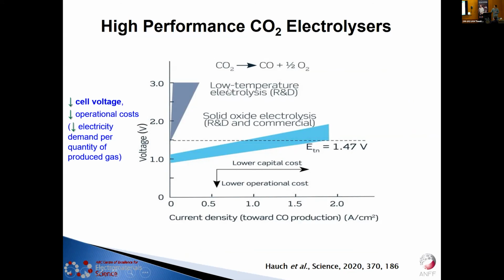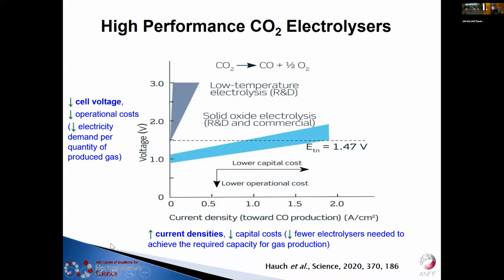At the moment, low temperature electrolysis needs quite a high voltage to achieve a reasonable current density. Ideally, if the benchmark is based on the water electrolyzer, we need about 500 milliamp, but there we are above 3 volt. Another point is that we have to have a high current density because it is economically important for the capital cost. That means we need fewer electrolyzers to achieve the required capacity for gas production. So this is where we stand now. I will discuss one of the reasons, the electrolyte, as one of the impacts here.